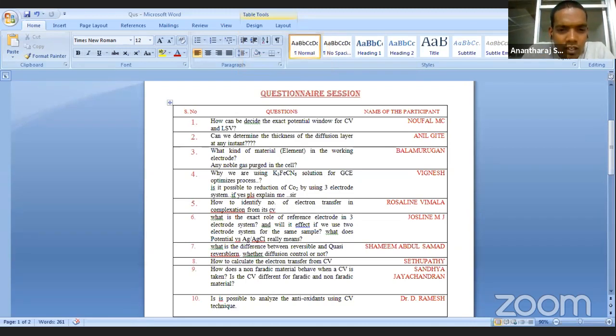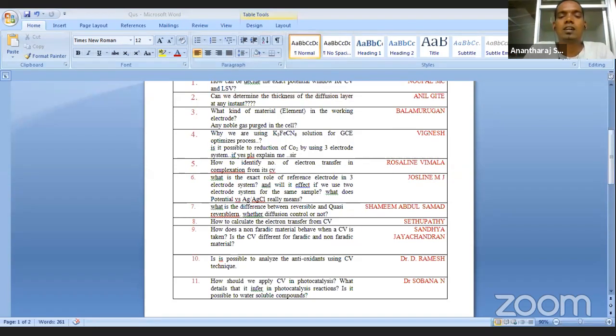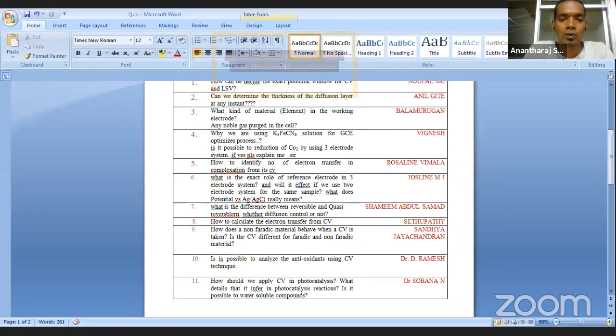Next: why are we using ferricyanide solution for the GC optimization process? Is it possible to reduce CO2 using a three electrode system? Yes, ferricyanide and ferrocyanide are a redox couple which is very famous for studying electrodes and charge transfer processes, because they are highly reversible and diffusion controlled when you perform with a macro electrode, and they occur via freely diffusing ions. So in the very first case I discussed, the peak to peak separation will always be close to 60 millivolt, the anodic and cathodic peak current ratio will be equal to 1, and the peak current will vary linearly with the square root of scan rate. So this is how you characterize your glassy carbon electrode. This is how you come to know whether you have perfectly polished your GC electrode or not.